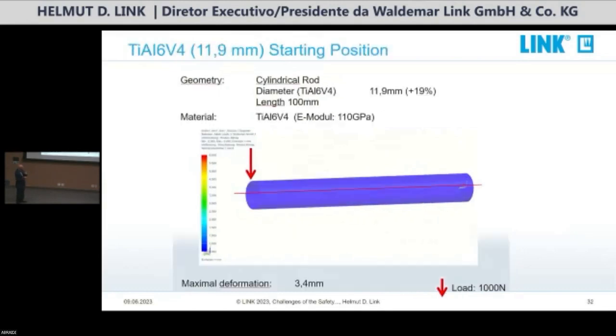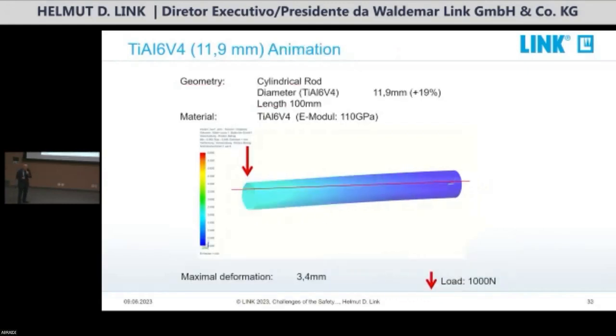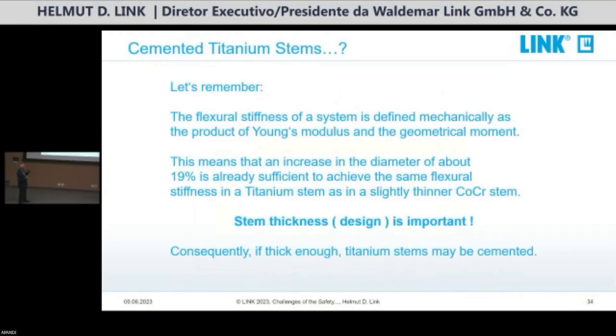But now, we increase the size of the titanium rod only by 19%. Still 110 gigapascal, still 1000 Newton, and the deformation is the same as the cobalt chromium rod. So in other words, if the size is right, you can also use titanium for cemented stems. That is something many surgeons, when we do it as custom made, for instance, and we provide titanium stems for cementing, the surgeon tells us, no, titanium cannot be cemented. Wrong. If the size is good, you can cement it, but the size has to fit the necessity to protect the cement. So let's remember, the flexural stiffness of a system is defined mechanically as a product of Young's modulus and the geometrical moment.